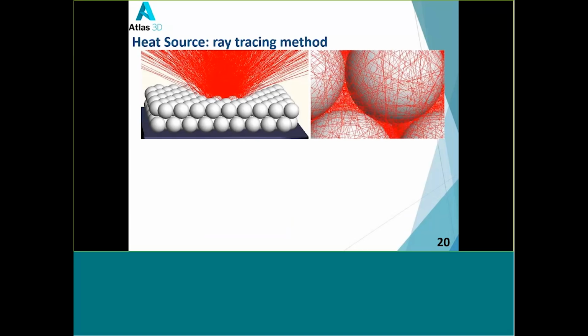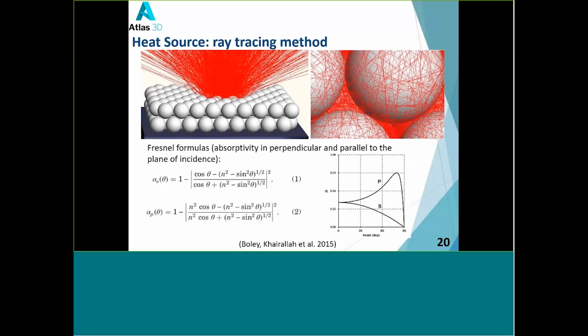The state-of-the-art modeling method for the heat source is called the ray tracing method. The idea is very simple. You model a single beam of laser with multiple rays, and you will track how each ray is reflected within the material. And every time you have a reflection, you need to calculate the absorptivity both in perpendicular and parallel direction to the plane of incidence. So in this way, if you calculate all the absorptivity of the rays, you will get a good idea how much energy is absorbed by the material.